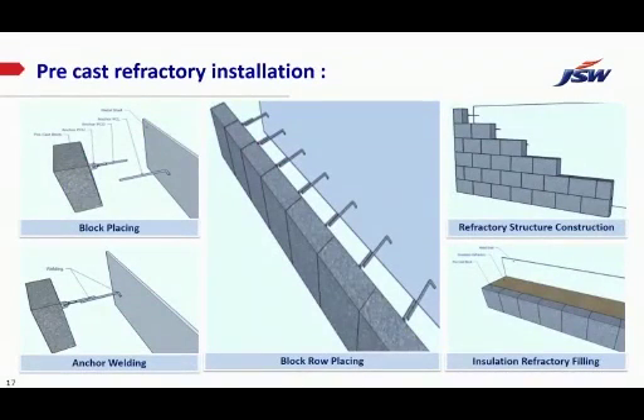This is the schematic arrangement of the precast installation. Here we can see the block placing side, where we build the L anchors on the metal plates and put the precast, and O anchors are welded with the L anchors, as can be seen in the anchor welding stages. By doing this, we make the block rows like that shown in the block row placing, and by every row the construction is completed, as shown in the refractory structure construction schematic. In a backup layer, we fill with insulation for thermal insulation to the metal plates.